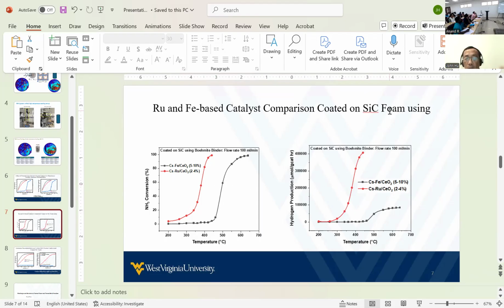We change the formulation. We also put it on the support because we know cesium is good. The only thing we do not know is whether iron is good or ruthenium is good. So we fix the cesium and then change the metal. We compare iron and ruthenium. So ruthenium is better. Okay, make sense?